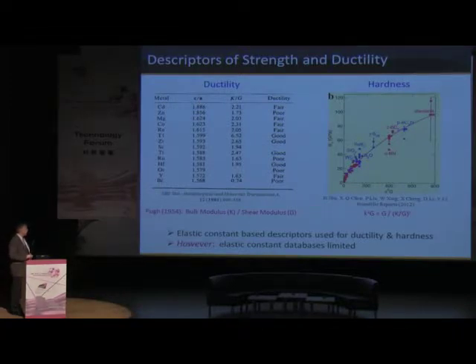Already in 1954, Pugh was telling us that this ratio of bulk modulus to shear modulus tells us something about ductility. This is a review from Mannu. Basically, the higher this K over G ratio, the better in terms of ductility. What that's saying is if you have a low shear modulus, it's easy to plastically deform the material. If you have a low bulk modulus, it's easy to break the material, to pull apart the bonds.